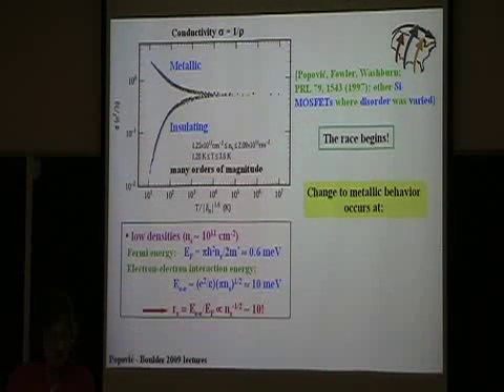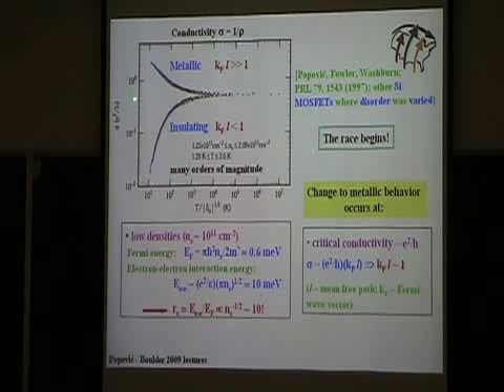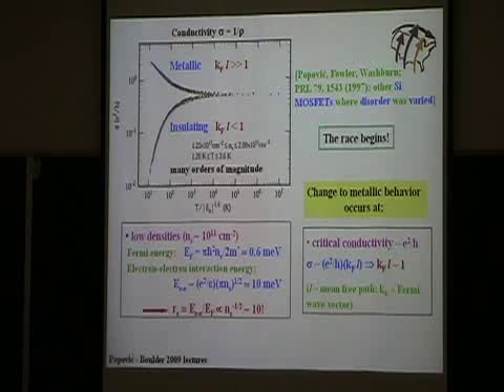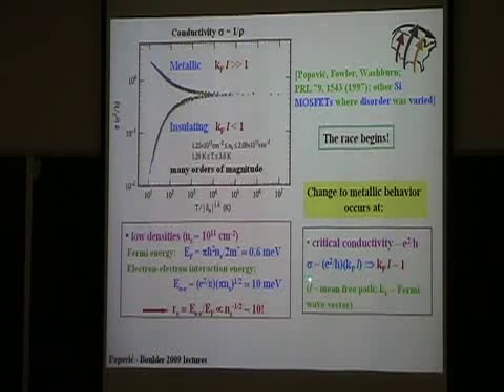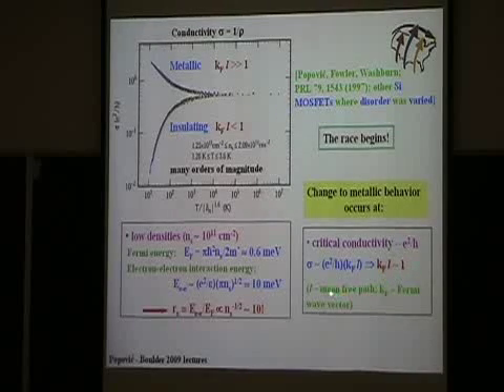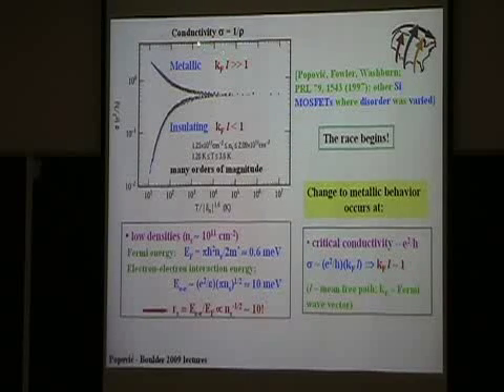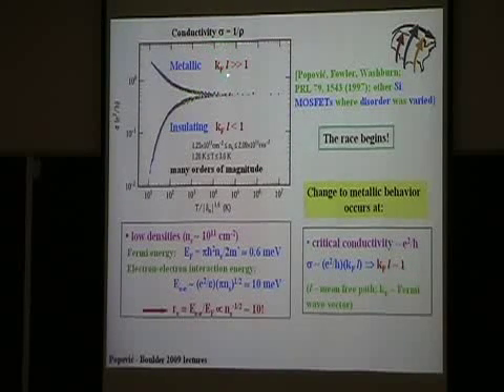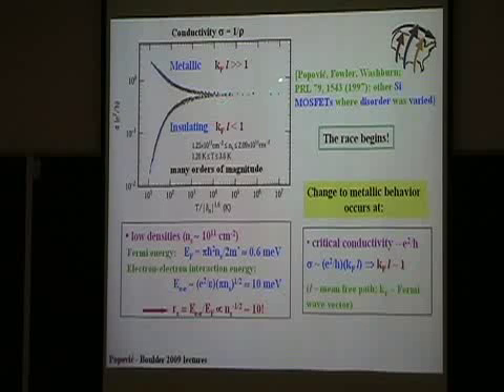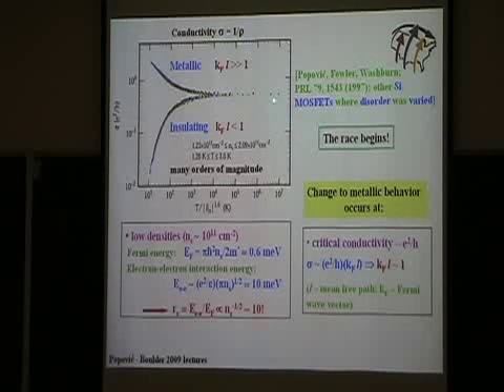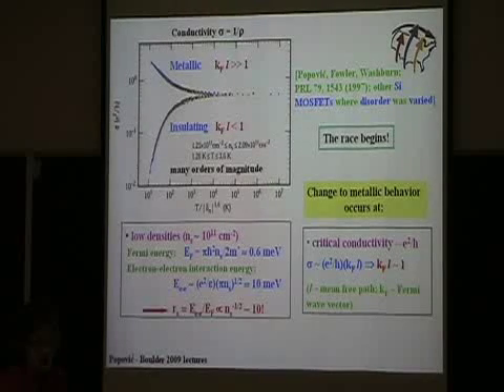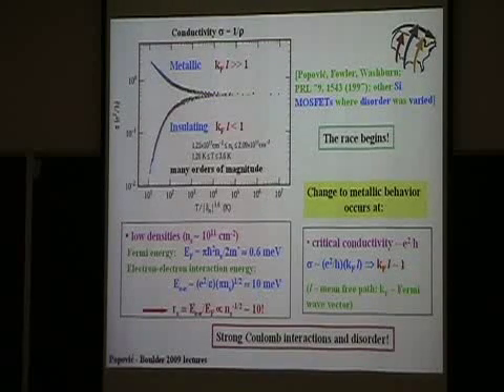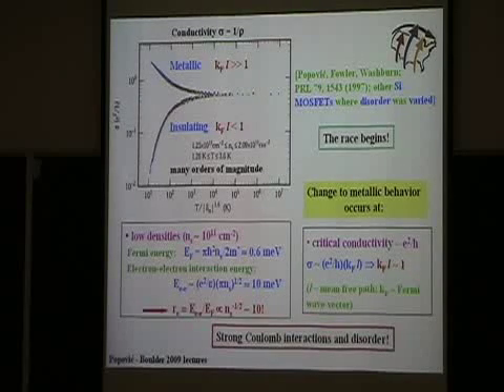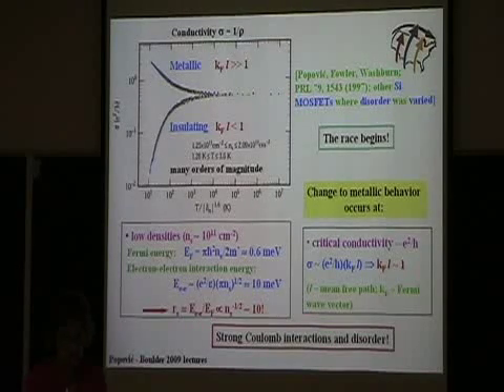Okay, so the other thing we notice is that the critical conductivity is of the order of e squared over h. And from the Drude expression in 2D, this tells us that k_F l is of the order of 1, where l is the mean-free path, and k_F is the Fermi wave vector. So in other words, whereas in the metallic case the mean-free path is much larger than the Fermi wavelength, so you have nice waves, when it gets to here, then obviously the disorder becomes important. So what we have is a case of strong Coulomb interactions and disorder. This is where the metal-insulator transition takes place. So these effects, I think, have to be taken into account.